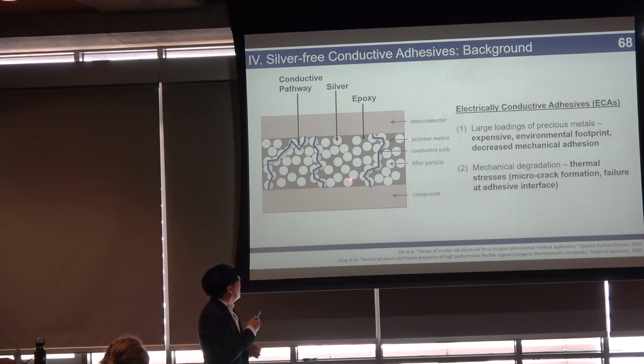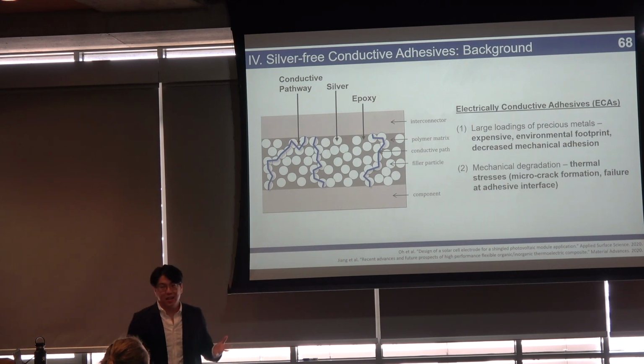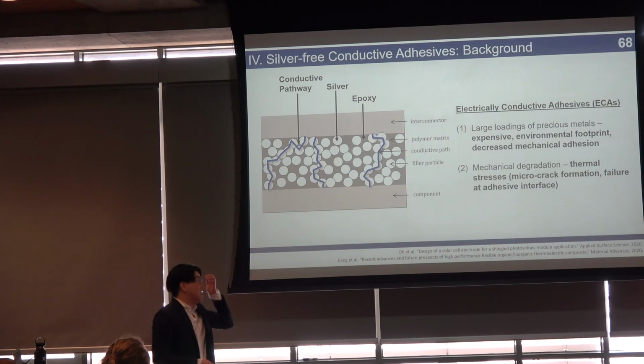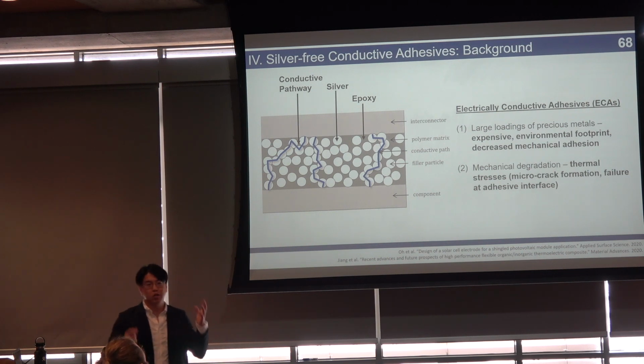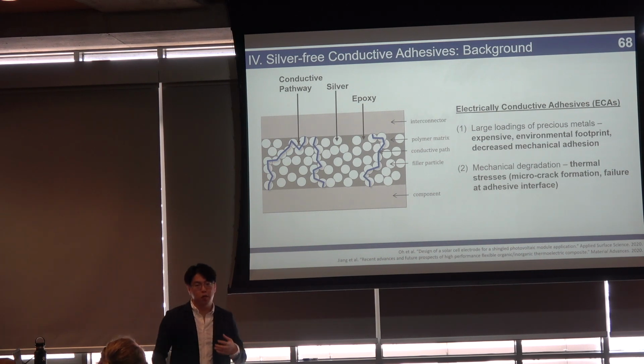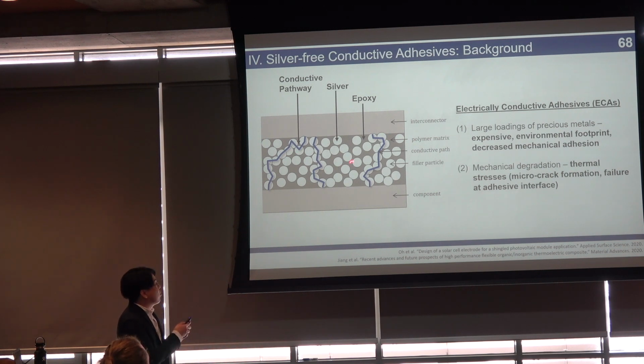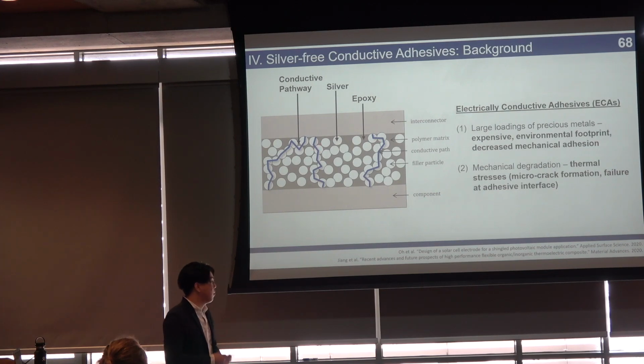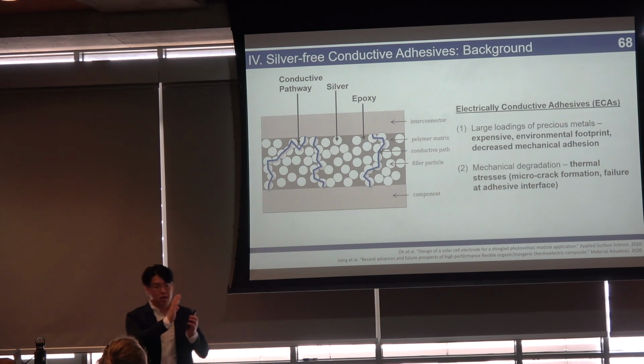And the other problem is that these two materials want to do different things. The silver wants to conduct electricity and not stretch, and the polymer matrix wants to do the opposite. It can stretch and do whatever, but it doesn't want to conduct electricity. So this leads to some mechanical trade-offs. For example, as your devices heat and cool over years and years and years, you might get migration of these silver particles into giant domains, and then your electronic pathways are no longer connected and no longer percolated. What you might also get is, for example, crack formation where the silver meets the polymer chain.